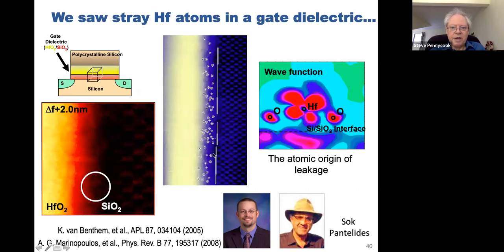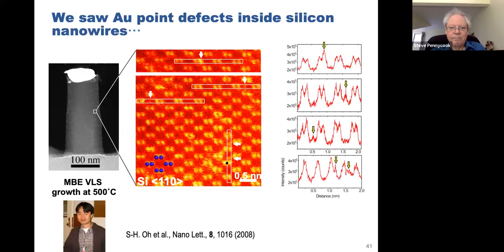But he was able to map all these dopants in 3 dimensions. You can see there's quite a high density. So Pantelides with a student worked on the wave function here. Showed that with this density, the wave function would overlap and you would get leakage. And this would explain rather nicely why the device was too leaky to be of use, too many stray hafnium atoms. Sang Ho was a postdoc at the time.